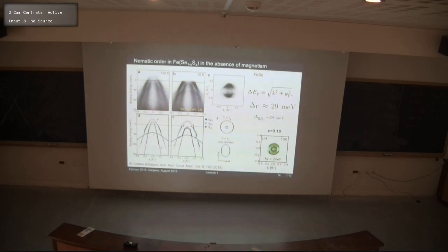And also, we see the distortion of the Fermi surface from the tetragonal case to a single elongated ellipse as another signature of the nematic phase. There are two ellipses here because the system forms domains as you go through the transition, which complicates life a bit. Now, there are lots of studies under strain, which I'm not going to talk about this time. But when we compare a system in the nematic state and outside, it's obvious that this C4 symmetry is preserved when we are in the tetragonal phase, whereas we break it inside the nematic phase.